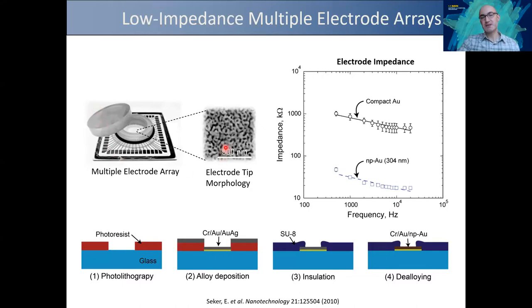We replaced the gold and the platinum with the porous electrode, and we used very standard fabrication techniques. You start with a glass, put on a photoresist, which is a photosensitive polymer. You expose it with UV light through a mask. And then you successively deposit a chrome adhesive layer, gold, and gold silver. Insulate the electrodes just to expose the electrode sites. And eventually, you dealloy it, so you have that nanoporous gold electrode on the sites.